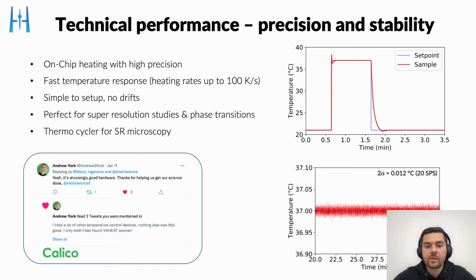The technical performance of the system was quite important to us. On the one side, it's very precise, so you can stabilize the temperature to a very high degree. As you see here, it's a time trace where the temperature stabilized to 37 degrees C, and we achieve a standard deviation below 0.01 degrees C over an extended period of time. In principle, due to its fast thermal response, the system is similar to a thermocycler for super resolution microscopy.